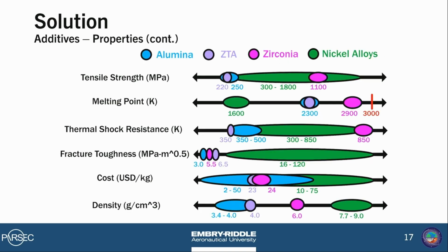So to summarize properties from a bunch of similar plots, we have a set of single axes here to show a bunch of different properties for ease of comparison. You can see that each additive has its own distinct, unique properties. With alumina and ZTA, for example, we have relatively low density and relatively low cost, but that also comes at the price of having a relatively low tensile strength and low thermal shock resistance. Whereas with zirconia, it's flipped, where we have a relatively high tensile strength, a relatively high thermal shock resistance, but it's also a little bit more expensive with a density about 50% greater than alumina and ZTA.